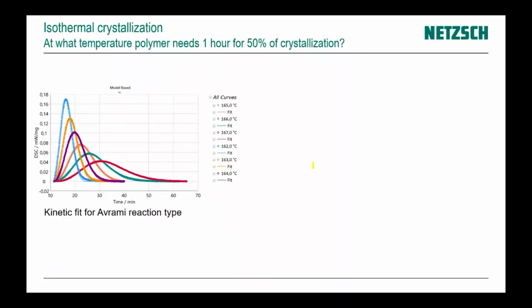And the next one is isothermal crystallization. Here we have crystallization of polyamide 12 at different temperatures. What is the difference here with the chemical reactions? For chemical reactions, a reaction will be faster if we have higher temperature. For crystallization, it is another direction. Crystallization will be faster if we have lower temperature because of the supercooling. And after that, let's answer the question: at what temperature does the polymer need 1 hour for 50% of crystallization?